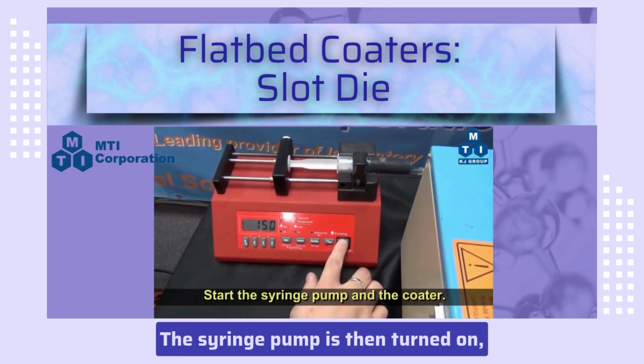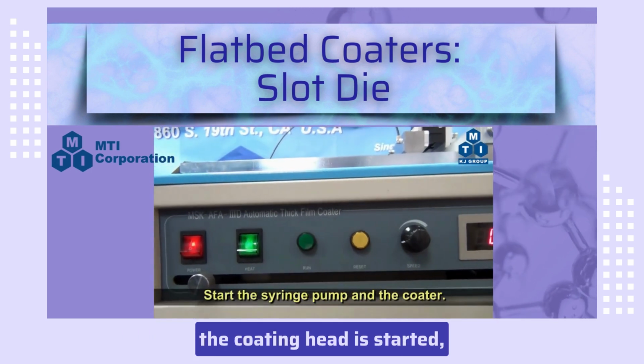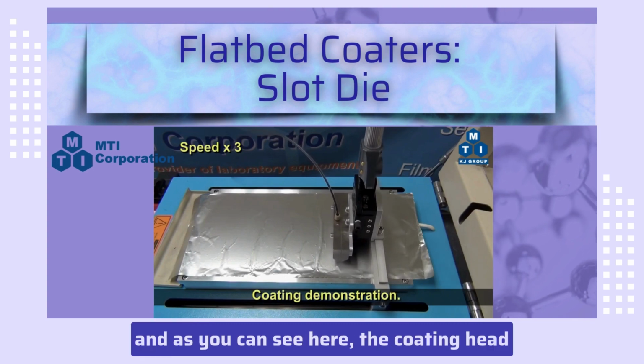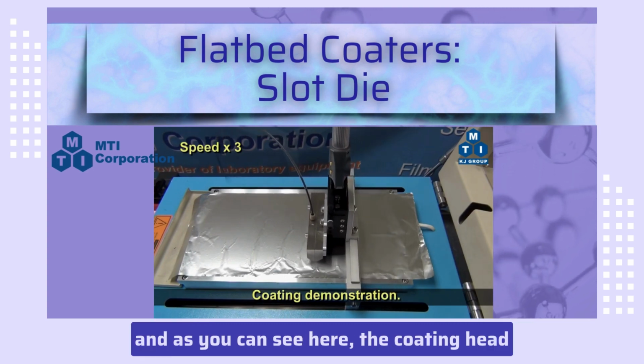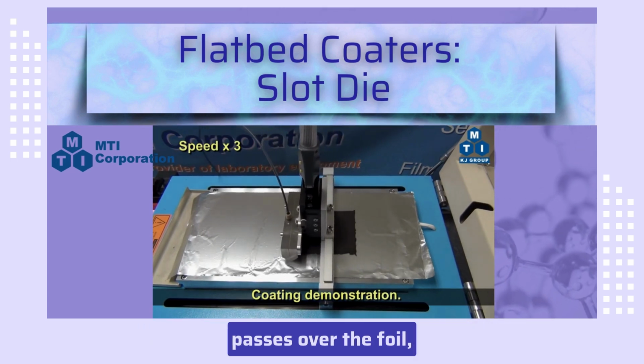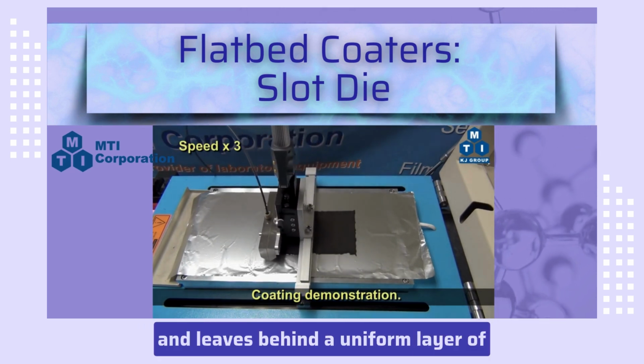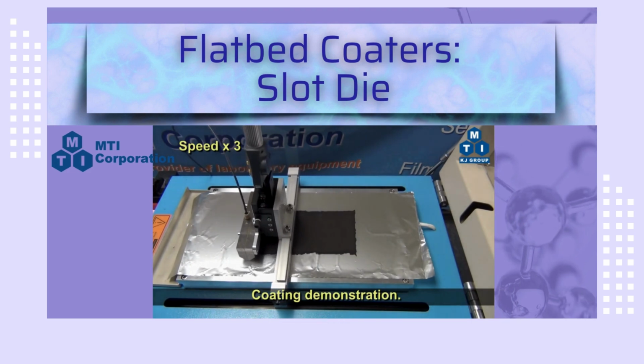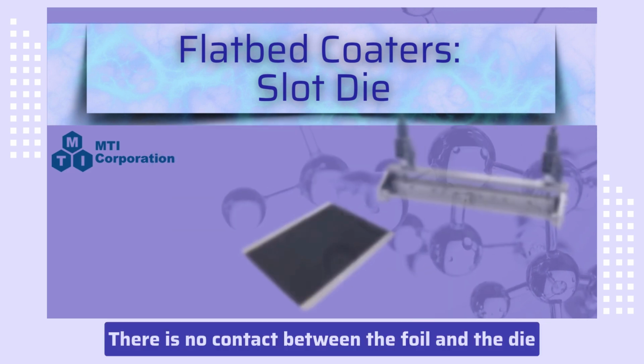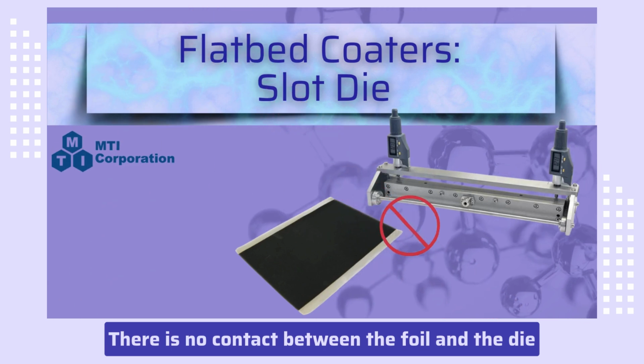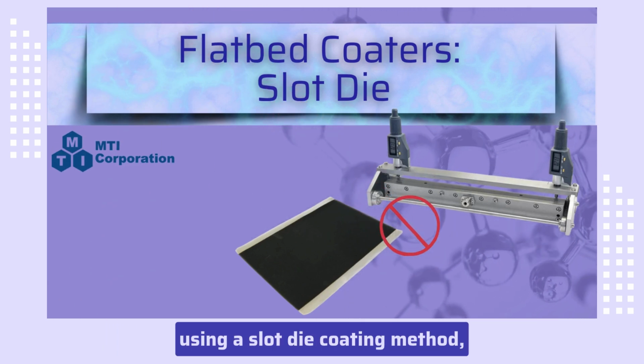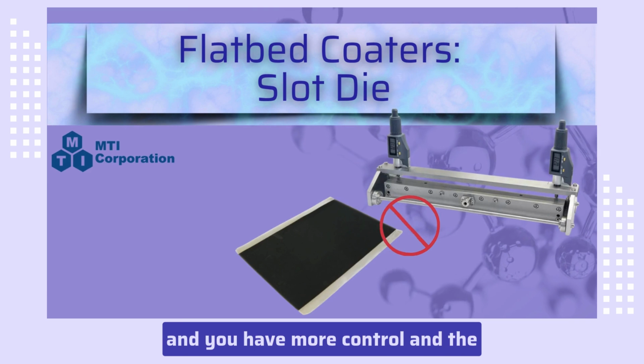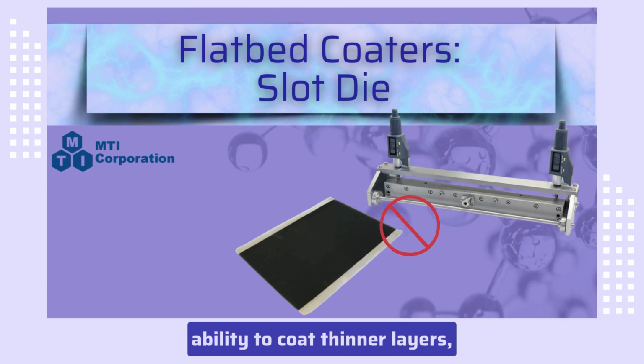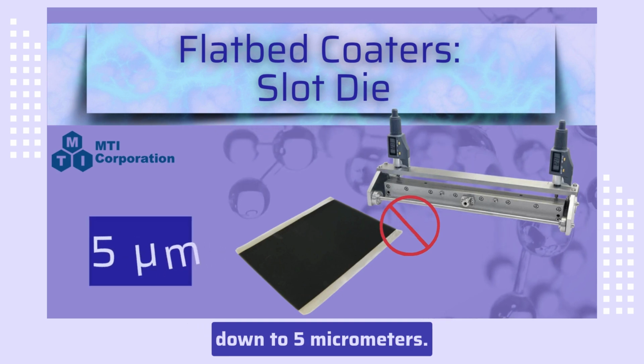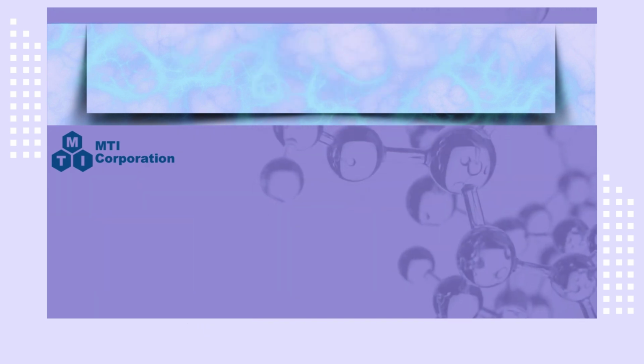The syringe pump is then turned on, the coating head is started, and as you can see here, the coating head passes over the foil and leaves behind a uniform layer of coating. There is no contact between the foil and the die using a slot die coating method, and you have more control and the ability to coat thinner layers down to 5 micrometers.